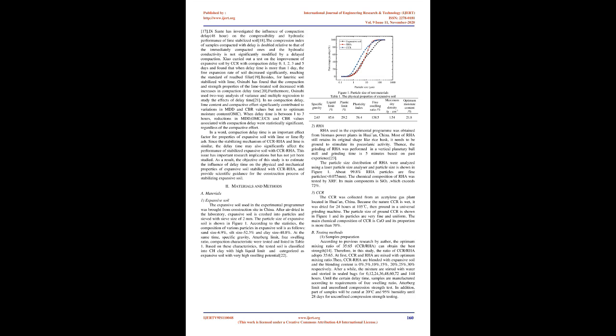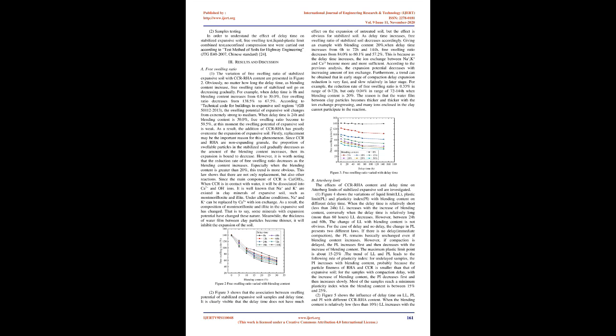2. RHA. RHA used in the experimental program was obtained from biomass power plants in Huiya, China. Most of RHA still retains its original shape like rice husk, so it needs to be ground to stimulate its pozzolanic activity. Thence, the grinding of RHA was performed in a vertical planetary ball mill and grinding time is 5 minutes based on past experience 23. The particle size distribution of RHA was analyzed using a laser particle size analyzer and is shown in Figure 1. About 99.8% of RHA particles are fine particles, <0.075 mm. The chemical composition of RHA was tested by XRF. Its main component is SiO2, which exceeds 72%.